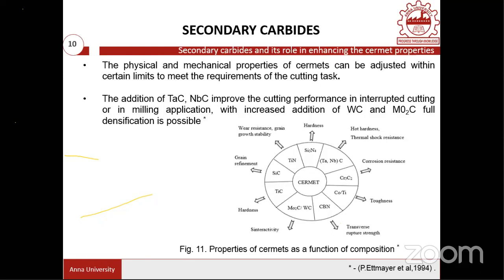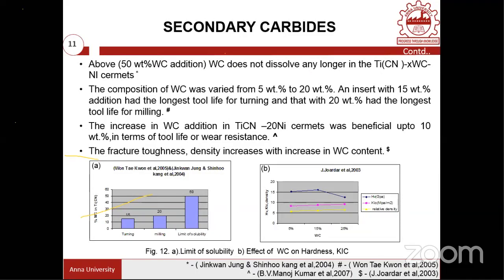Then obviously the tungsten carbide and molybdenum carbide are going to add sinterability. That means they are going to improve the wettability of the titanium carbonitride. And during the sintering operation, this helps to have good sinterability. Good wetting is an initial, required phenomenon to improve the sinterability. So the CERMET compositions should also have these binders as well as this sintering aid material.